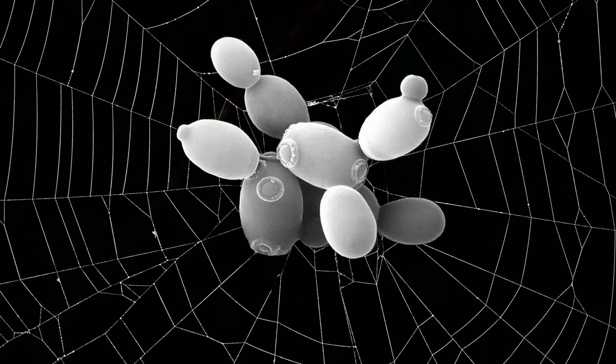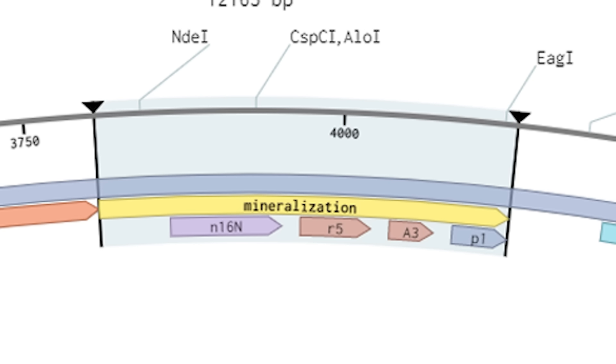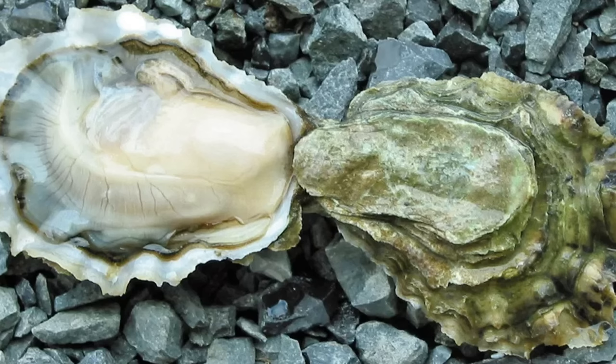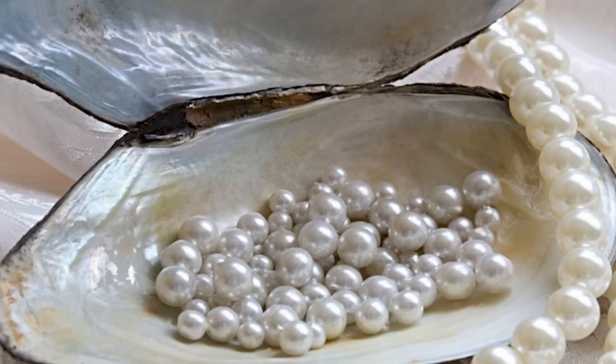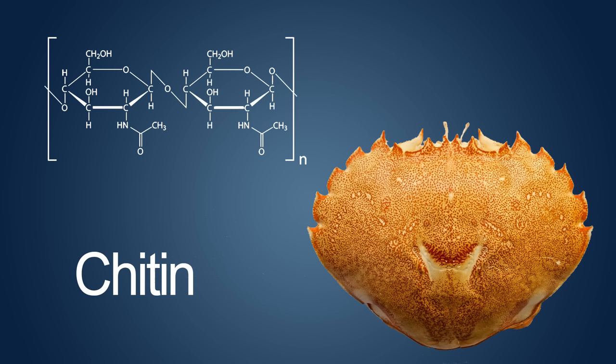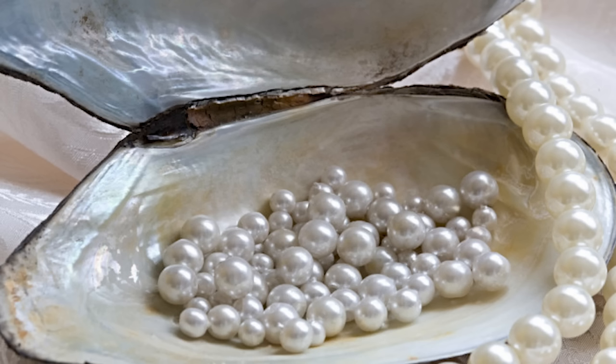The reason I did this was because I wanted to make sure the silk had extra properties. For example, the first peptide, taken from oysters, should collect calcium onto the silk. If carbonate ions are also present, this will turn into calcium carbonate, which is basically how shell forms. In fact, this same peptide also binds to a molecule called chitin, which is one of my all-time favorite materials. In theory, this should make the silk mineralize into a hard, tough material, very similar to mother of pearl if exposed to the right chemicals.